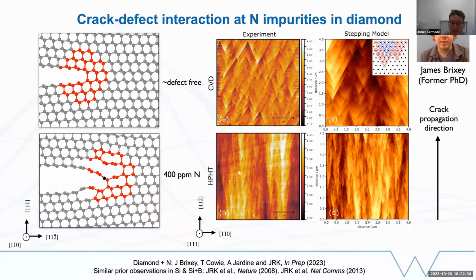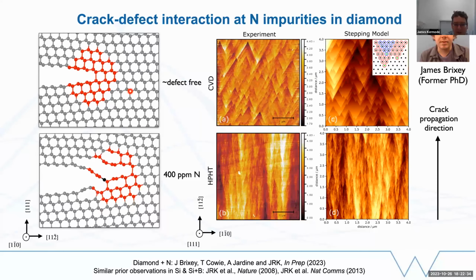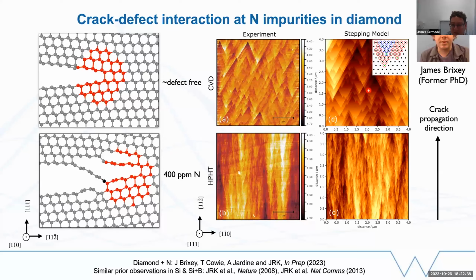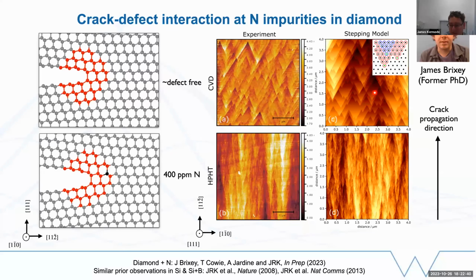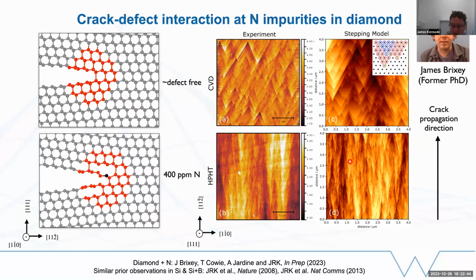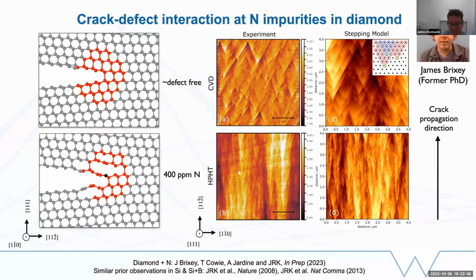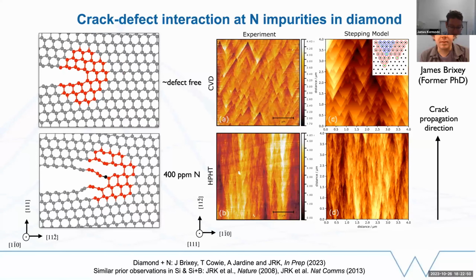And actually, we can confirm that with a simple mesoscale model that's informed by the atomistic simulations. We can put in the required concentration of defects, and we see models of the emerging fracture surface that are in good agreement with what's observed experimentally. So it gives us confidence that this mechanism could explain the emerging fracture surface here. So this is a good example of what we can do with QMMM.